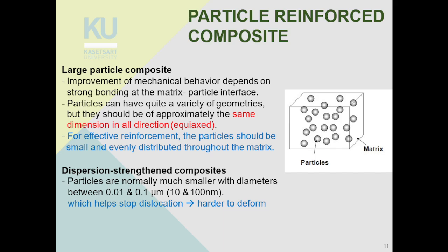So when the particles are small, they can be dispersed more evenly throughout the material. And when they are this small, they are in the same length scale as dislocation. Right? Dislocation is a defect in the material, right? And material can be deformed by moving the dislocation. So when you have these small particles in there, in the same length scale of dislocation, these particles will try to stop the movement of dislocation. So making the movement of dislocation harder, that will make it stronger. Right? The material is stronger because the dislocation is more difficult to move.